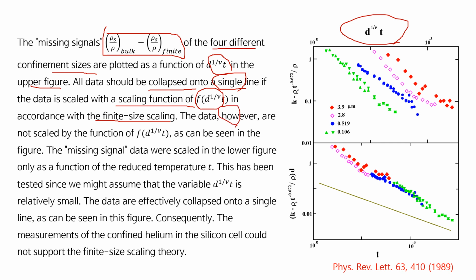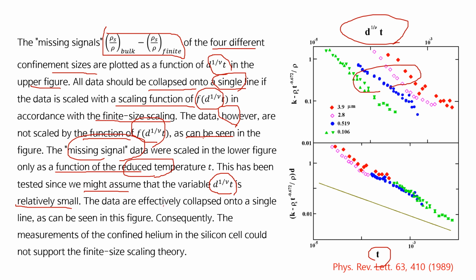However, the data are not scaled by this function, as can be seen in the figure. The missing signal data was scaled in the lower figure only as a function of the reduced temperature T. This has been tested, since we might assume that the variable d to the 1 over nu t is relatively small. The data effectively collapsed onto a single line, as can be seen in this figure. Consequently, the measurements of the confined helium in the silicon cell could not support the finite size scaling theory.